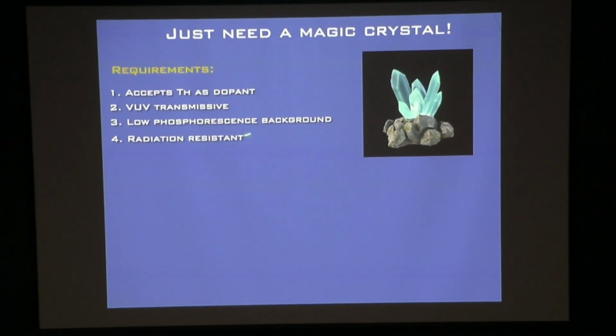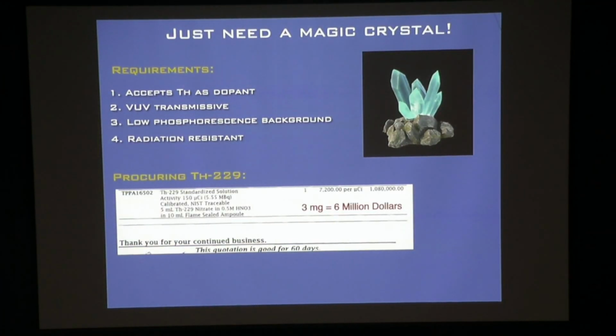And then you don't want it to glow from all the radioactivity inside of it, like the uranium dinner plates that glow in the dark. That would be bad because we're trying to excite a transition and see photons. So we worked for a very long time to try to meet these. Another problem was we thought at a minimum a couple milligrams of thorium-229. You would think that's not that much, but the very first quote we got was $6 million. Yeah. Luckily, they gave us 60 days to think about it.